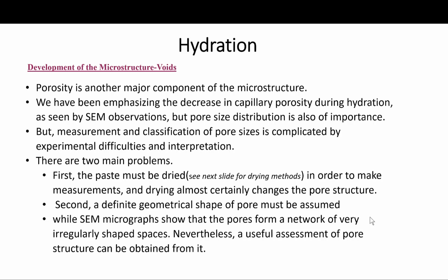First, the paste must be dried in order to make the measurements, and drying almost certainly changes the pore structure. I will show the drying methods we talk about in the next slide.